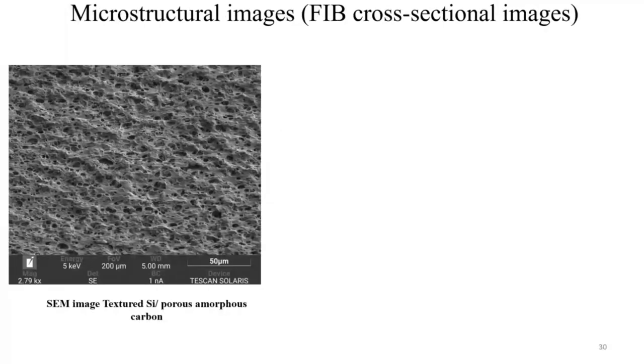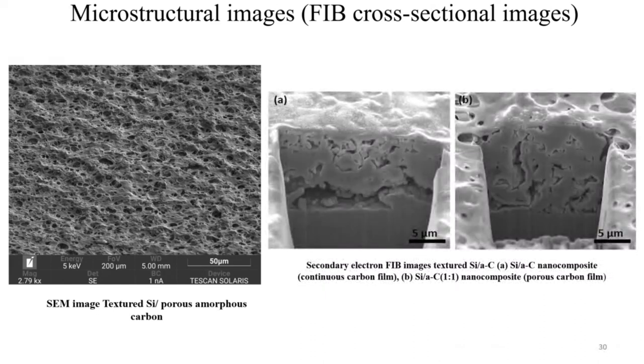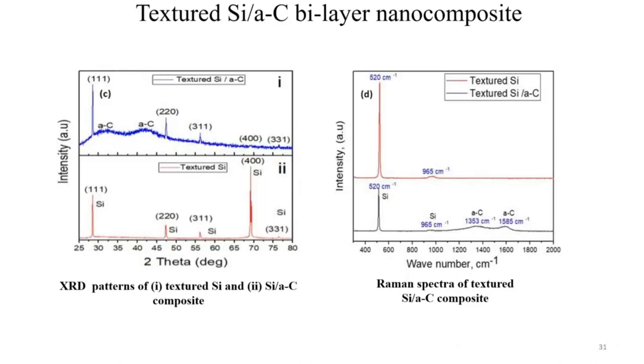And upon pipetting the precursors directly on the nanostructured surfaces, allowing them to dry, and also etching with HF, we produced a porous amorphous carbon layer, which sat directly on top of the textured silicon wafer surface. And this was also confirmed through FIB-SEM images. Now, the XRD analysis confirmed the presence of both silicon and the amorphous carbon coating, which forms the bilayer nanocomposite, and Raman spectra as well confirm these phases present on top of the silicon wafer.